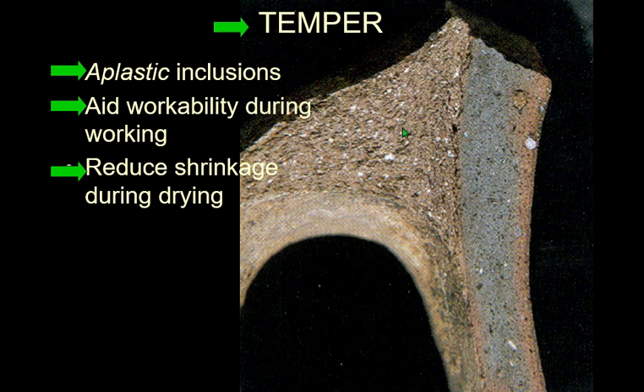Because the clay shrinks, if this had been added and had the same amount of clay, it would probably shrink so much it would fall off. Of course, another alternative would be to attach the handle to the vessel while they're both at the same degree of dryness. But this is probably some sort of mass production at the time, adding the handles after making a lot of vessels.